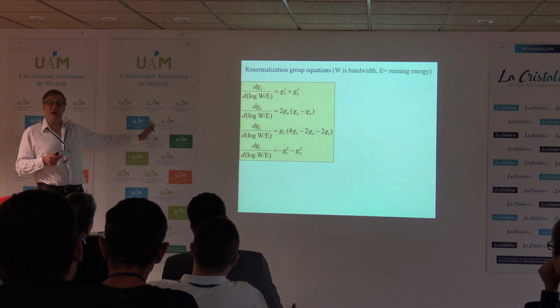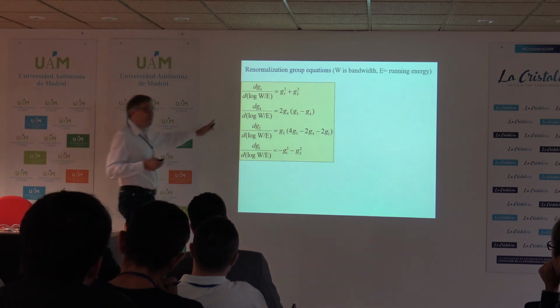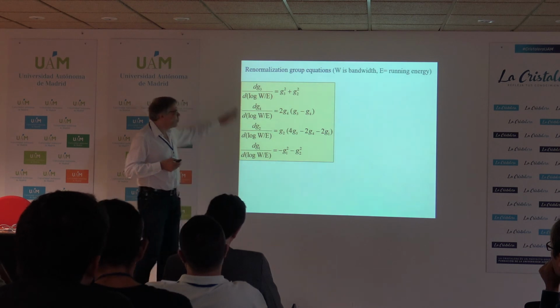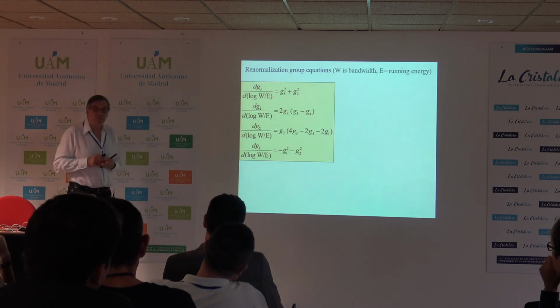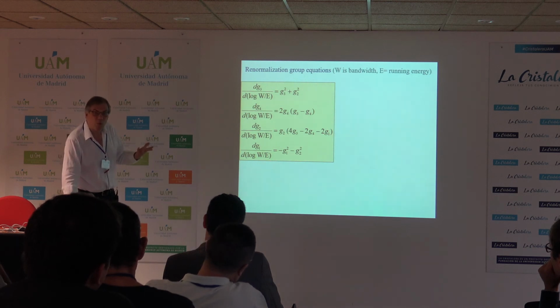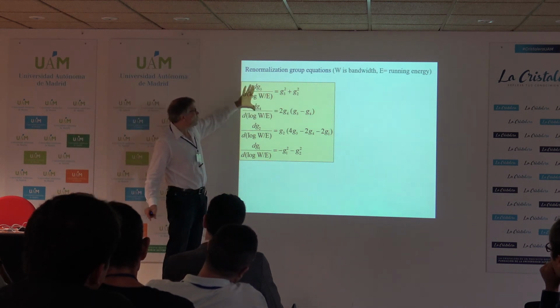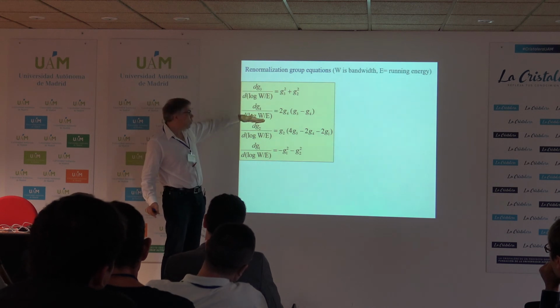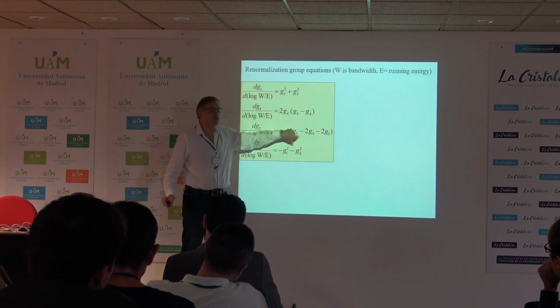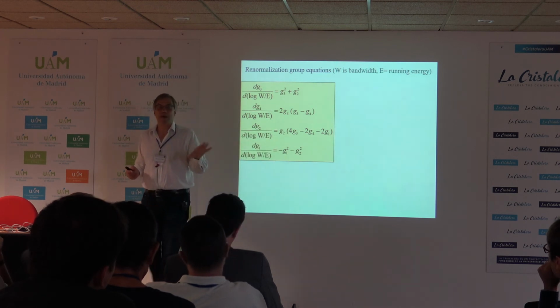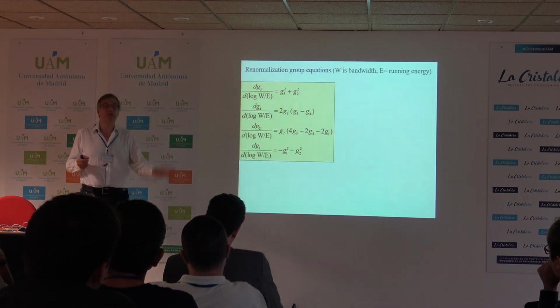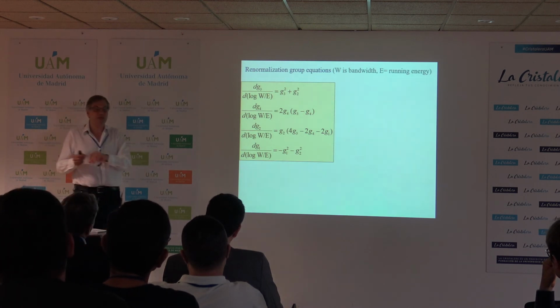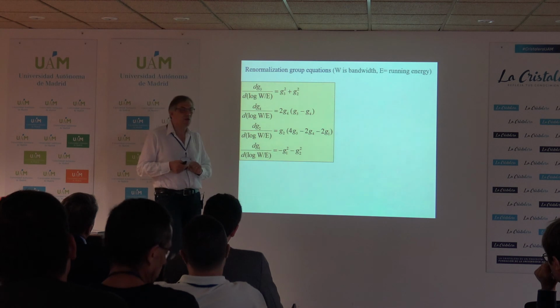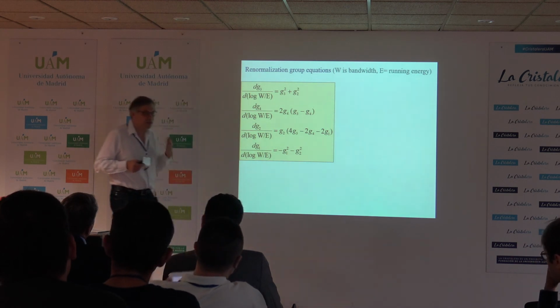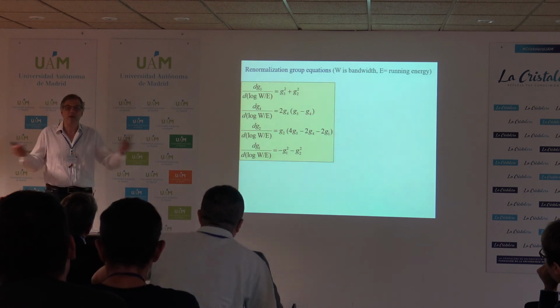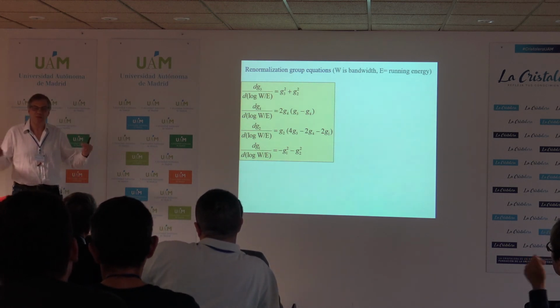Let me not discuss how to derive them, but they're derived in a pretty standard way, although it requires a little bit of work to derive these two equations. Now, we need to solve these equations and see what the flow is. If I only focus on these two couplings and neglect all particle-hole channel, then I will not convert water into wine. I will start with repulsive interaction, I will continue with repulsive interaction, and repulsive interaction will just get weaker and weaker as I go to smaller and smaller energies. This is a known effect. There is no way, working with only one channel, to change the sign of interaction.